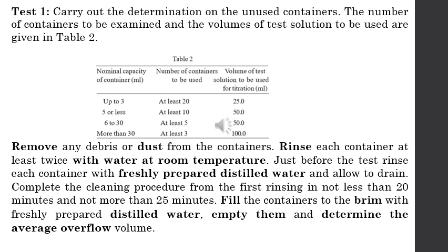Now what is done is we have to remove the debris or dust from the containers by rinsing the container at least twice with water at room temperature. Now this water which is used for rinsing should be freshly prepared distilled water. The rinsing time is also mentioned, that is it should not be less than 20 minutes and should not be more than 25 minutes.